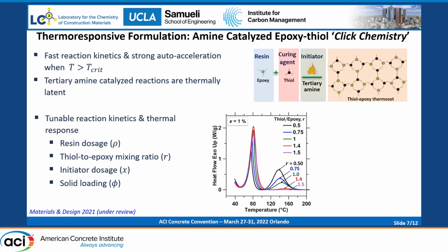So I will show you one example of how we can play with these formulation parameters. This shows a DSC thermogram of epoxy-thiol mixtures. Basically, you see two thermograms here, which correspond to two curing reactions. One is the epoxy-thiol reaction, which is happening at the lower temperature here. And another one is the epoxy homopolymerization, if you have any excess epoxy in the formulation.